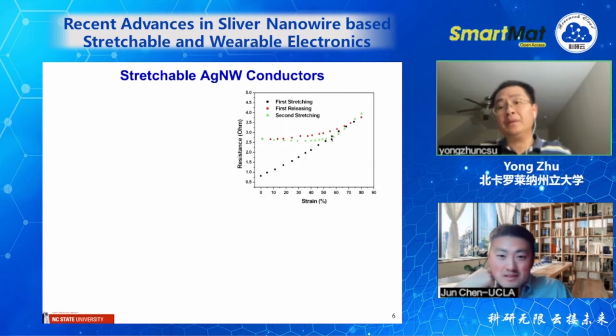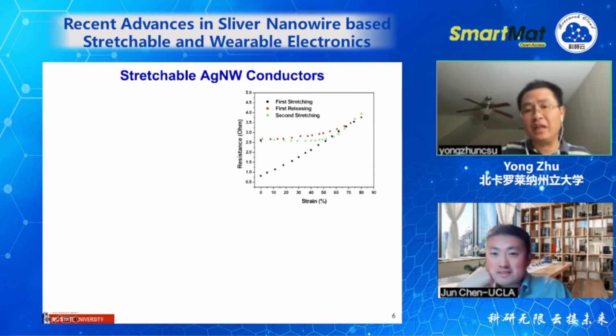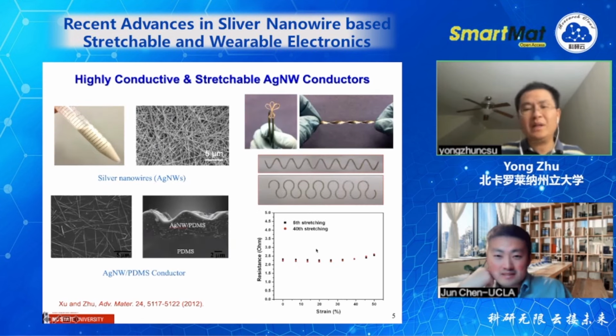Okay, then it depends, right? If you stretch it and stay within 50%, then it's more or less constant. If you go beyond that, it will change. We studied many cycles, hundreds, even thousands of cycles. Here I'm showing the fifth and the 40th cycle. You see the resistance is nearly constant up to 50%, and for hundreds of cycles we can have a repeatable process.